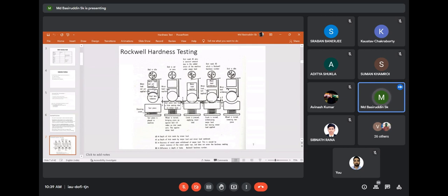So we try to set the test space such that initially the steel ball touches the sample surface, okay? And if we restrict the lateral movement of the test space, then we have to apply a certain minor load. In the Rockwell hardness test, we generally put a minor load of, let's say, 10 kilo, okay? And we must be assured that at 10 kilo load no plastic deformation should happen. Only elastic deformation could happen, but that particular elastic deformation will restrict the lateral movement of the test piece. Okay,